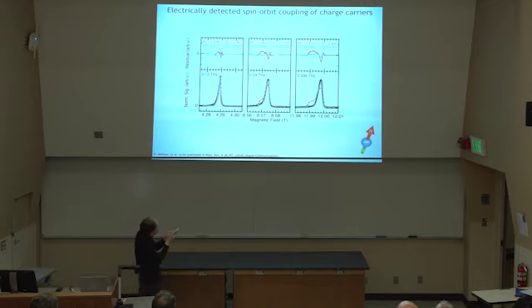And if you compare this calculated data with the experimental data, you see that these red cases just don't fit. There's no agreement. So that also shows that we can't just reproduce anything. But then you see the blue works really well. And that actually excludes the assumption of g-strain, which basically makes us more selective for the description that we make here.